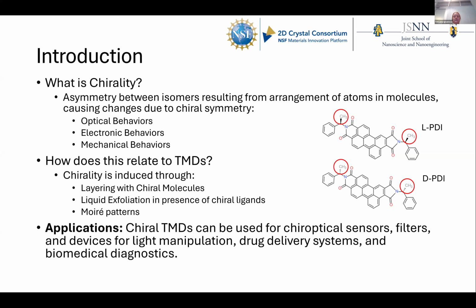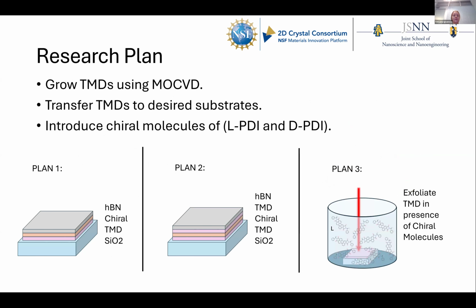But how does this relate to the TMDs? You can induce chirality in multiple types of TMDs by layering them with the chiral molecules and liquid exfoliating them in the presence of a chiral ligand in water or other solutions. They can be used for chiral optical sensors, filters, and devices for light manipulation and such. So my research plan going to PSU was to grow the TMDs using MOCVD and then transfer them onto the desired substrates, with hopes to introduce the chiral molecules while I was there, but I did not get to that. So these are my three plans.